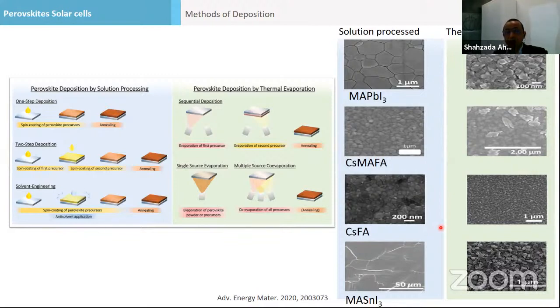And the good thing about thermal evaporation is that you can control the thickness to exactly nanometer, and that will give you high reproducibility. We talk about bigger grains, and this is good. We hypothesize that if you do thermally evaporated, the grains are even smaller, with different types of perovskite. This is methylammonium, this is triple cation CsMAFA, this is CsFA, cesium formamidinium.